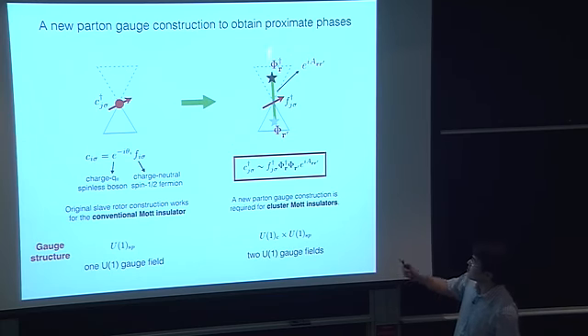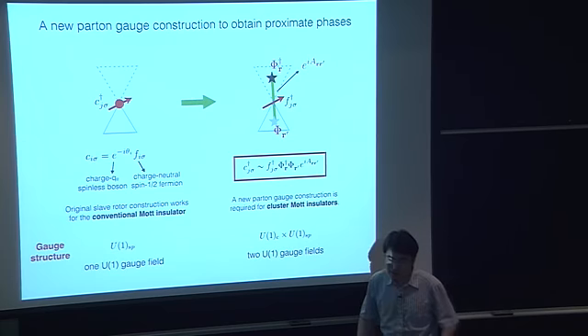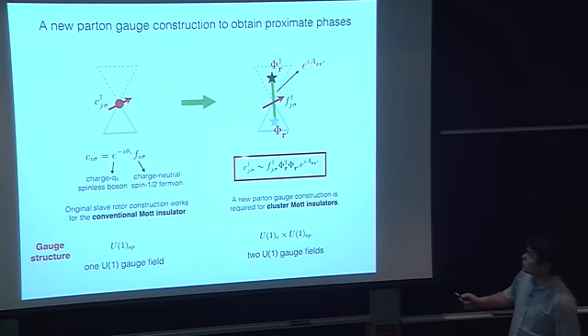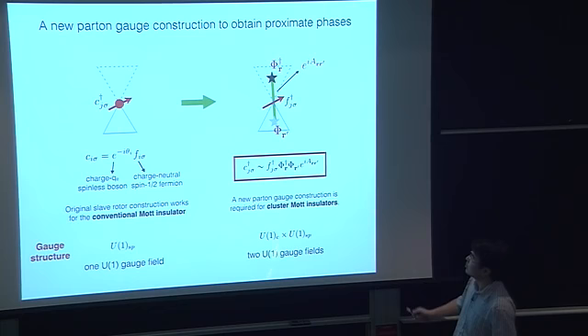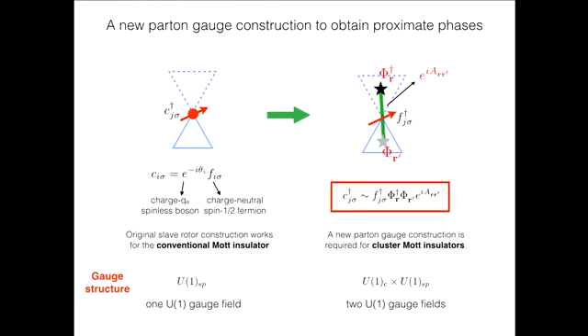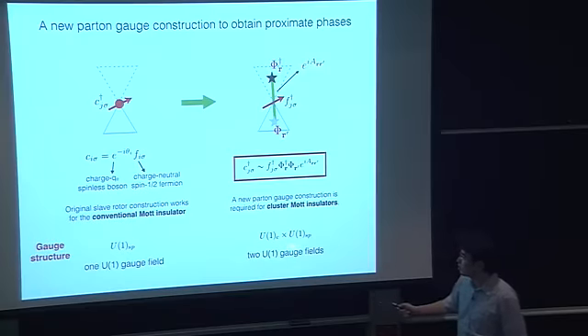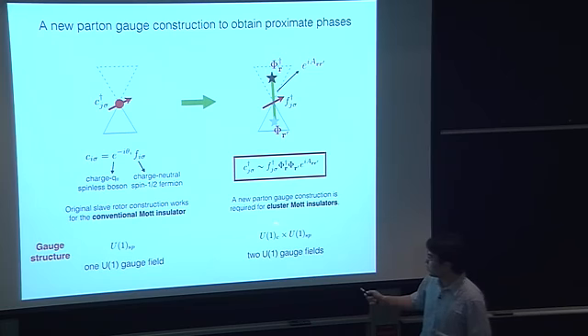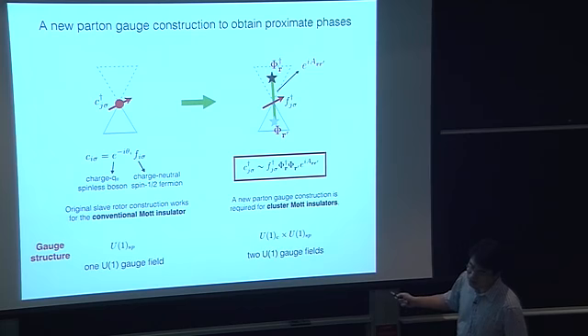For the cluster Mott insulator, the parton gauge construction needs to take into account the additional gauge structure in the charge sector. So in addition to writing the electron as a charge rotor times the fermionic spinon, we need to further decompose the charge rotor into two parts, because adding a charge violates the localization condition on both up and down triangles. That's like adding a gauge charge onto the up or down triangle. So we fractionalize the electron into three parts: one fermionic spinon and two charge rotors. This is a new type of parton construction to capture the two U(1) gauge structures in the theory: a U(1) gauge structure in the charge sector, and a U(1) gauge structure which causes the spin-charge separation.